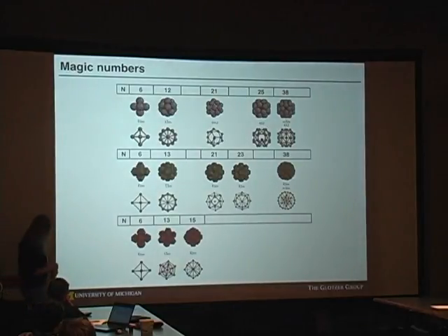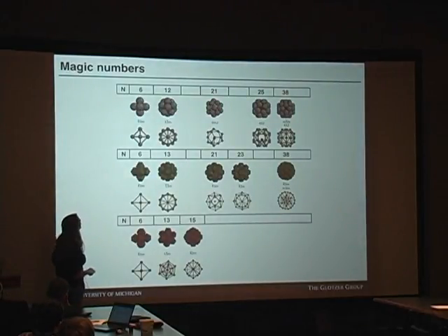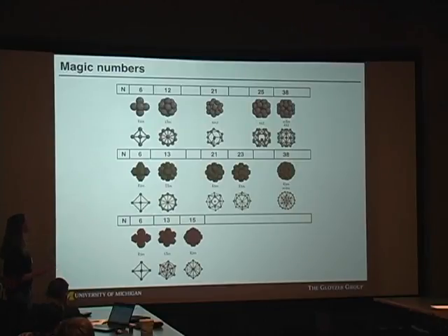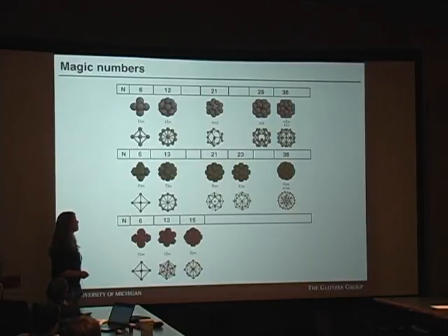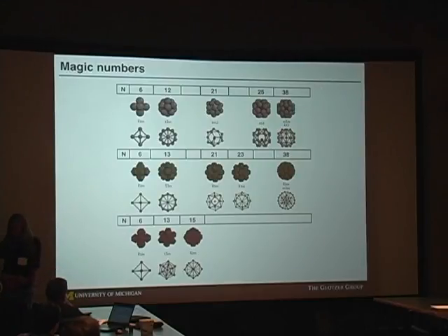And here's where I'll start to wrap up. I was hinting at this earlier, but when you look at the more spherical platonic solids, you see that in a lot of cases, especially for the magic numbers, these match the densest sphere clusters. It's a different n, but this is still an icosahedral geometry. There's just one particle at the center in these cases. At n equals 21, it's a similar story, and the n equals 38 cluster is special because it's cubically close packed, but it's also common among spheres, and then the less spherical platonic solids.